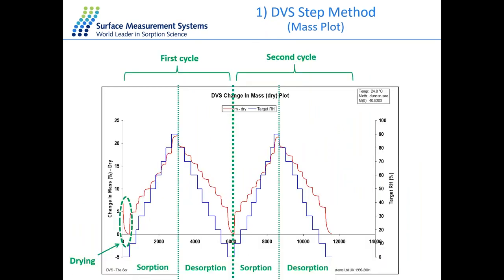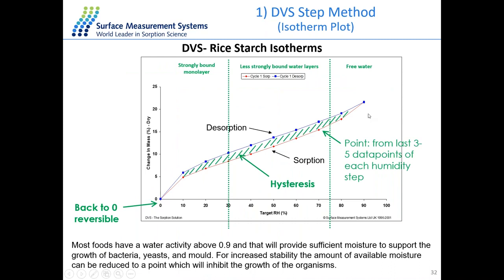At the end of each step here, we're reaching a stage of equilibrium. If we collect some points here, we can take these points and plot an isotherm plot. In this case, we have our absorption and our desorption and our hysteresis gap in the middle. What we can see is that we are going back to 0, and this again suggests a reversible experiment. So it's quite interesting to have an isotherm along with your mass plot.